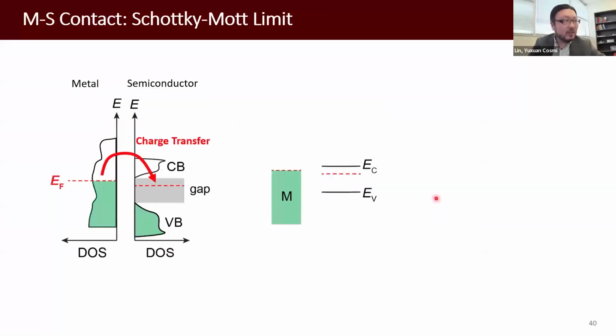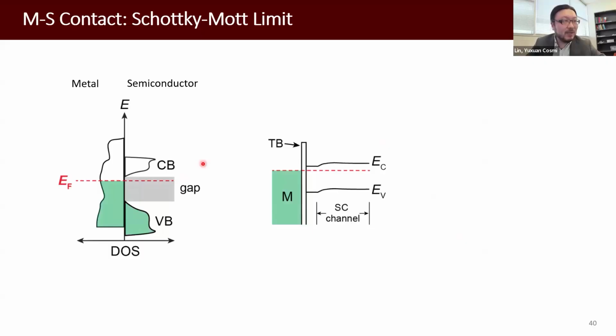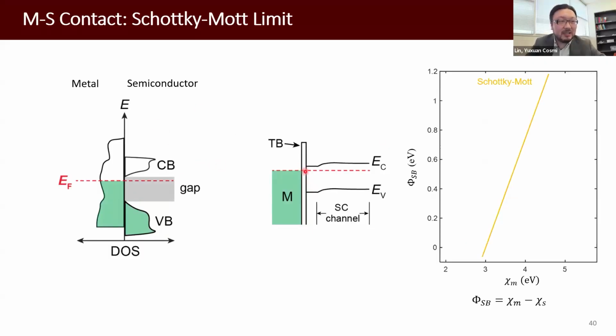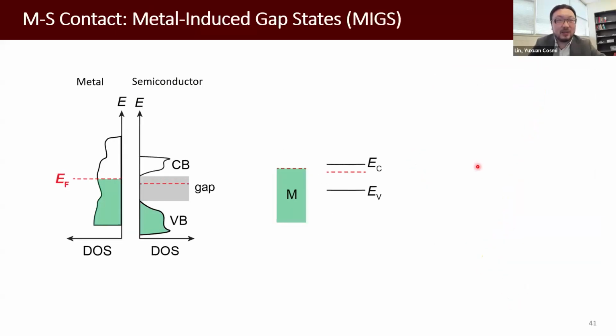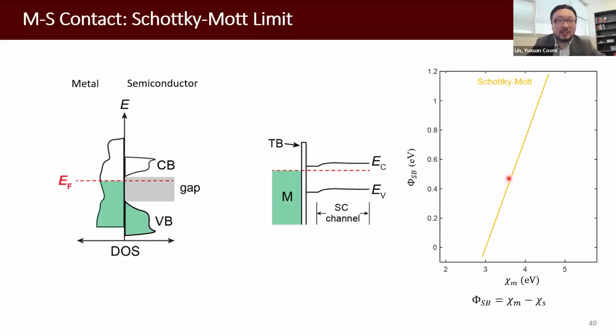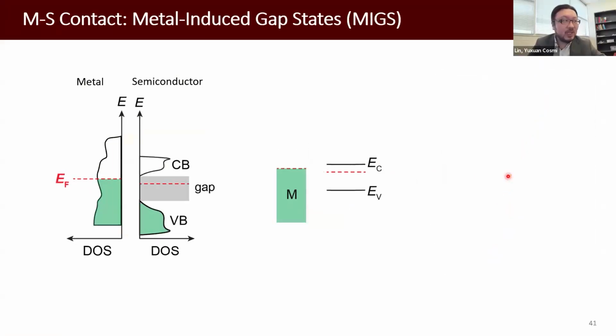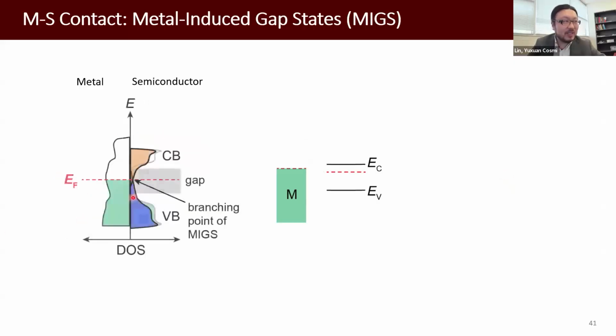If you think about this problem fundamentally, in the ideal case, if only charge transfer happens at the metal-semiconductor interface, there's a Schottky barrier. The barrier height is determined by the work function difference between the metal and the semiconductor. If you plot barrier height versus work function difference, it should follow a line with a slope of 1. But in reality, there is hybridization of the electronic states.